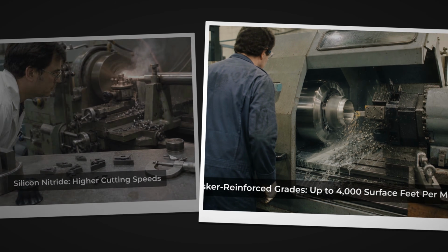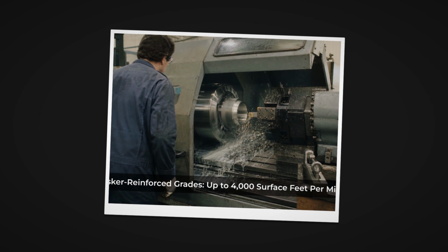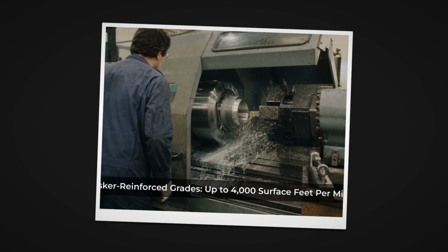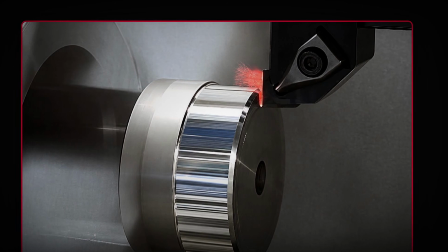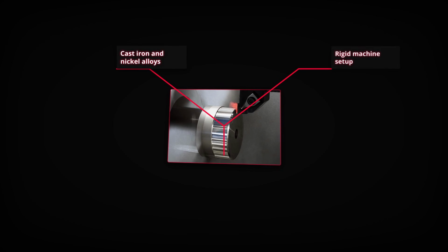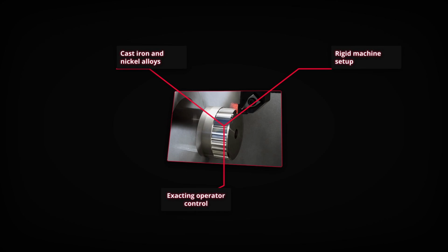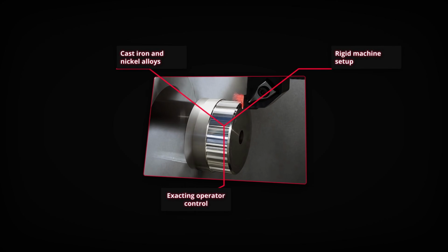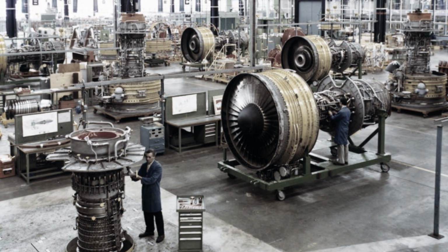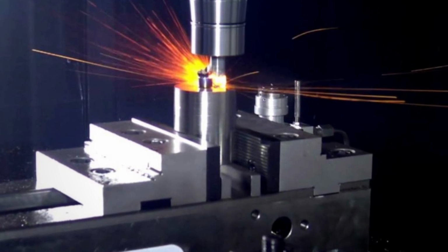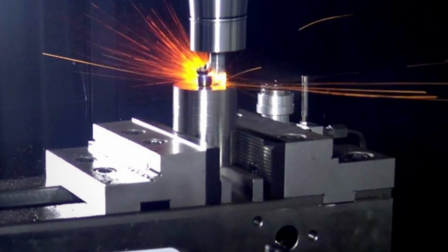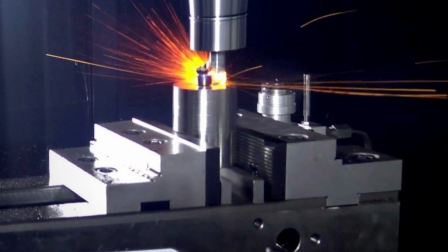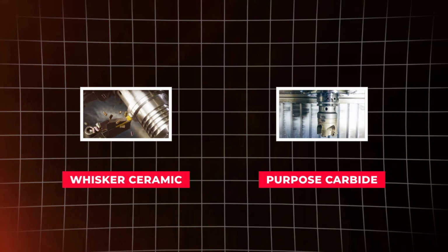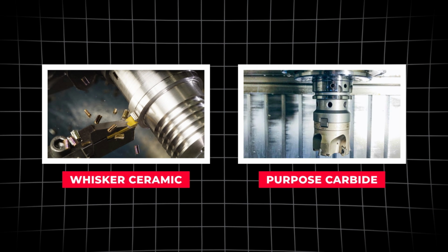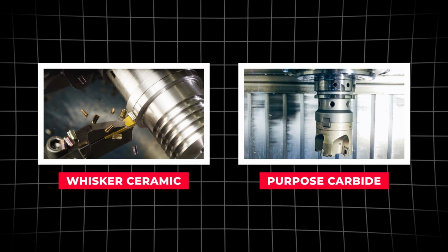Then silicon nitride and whisker-reinforced grades pushed cutting speeds toward 4,000 surface feet per minute in cast iron and nickel superalloys, provided the setup is rigid and the operator forgives nothing. This is where the jet engine's bill came due. The superalloys that shrug off combustion heat also dump cutting heat straight into the tool, and it took whisker ceramics and purpose-built carbide grades to machine them at production rates.